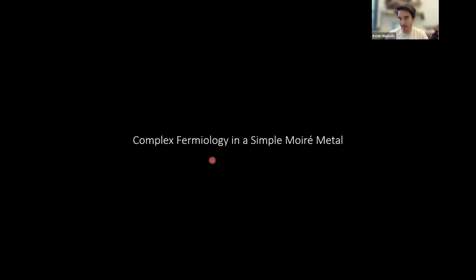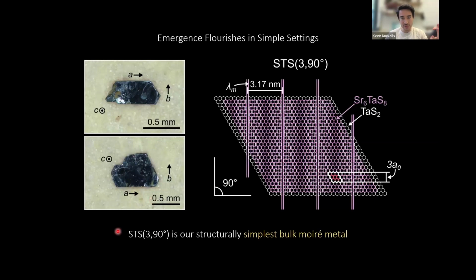So with the time I have left, I want to tell you about a deep dive into the fermiology of our structurally simplest and our highest mobility Moiré metal that we discovered in this entire phase space. So I'll remind you of that structure. We call this compound STS390, and it's our structurally simplest bulk Moiré metal because effectively the only interlayer coupling effect that we see is this long wavelength Moiré modulation of about 3.2 nanometers. And so this will give us a really nice testing bed for understanding the distinct influence of a Moiré superlattice in just an isotropic clean metal.